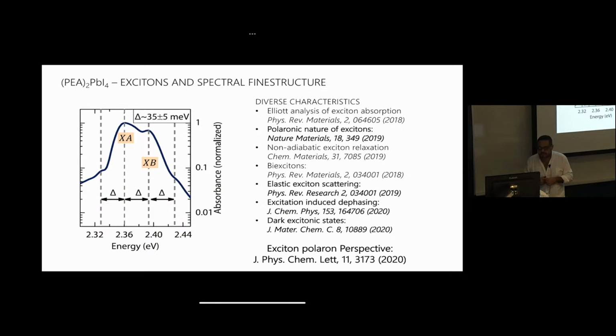So in order to also participate in the development of methods, not as directly, but through our colleagues, electronic structure calculation methods that really take into account all of these interactions, one would have to look at this. And that was another general context. So you're a spectroscopist, and so you say, okay, if I'm saying that this exciton here has a different lattice dressing, it perceives the lattice motion differently than this one, what I need to do is a resonance Raman experiment. In a resonance Raman experiment, you would excite with a laser that is resonant with an optical transition, either XA or XB.